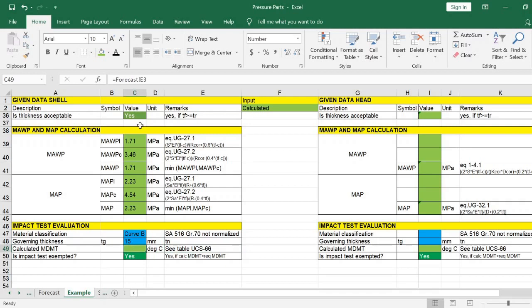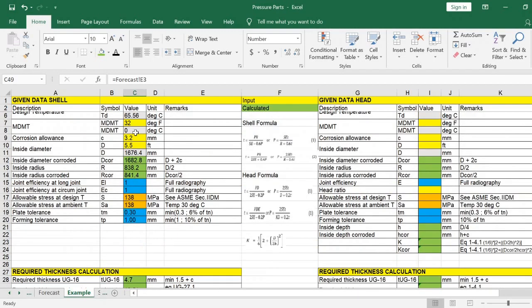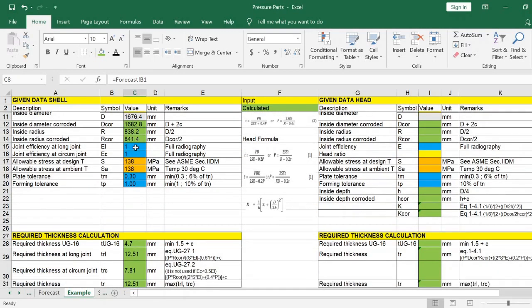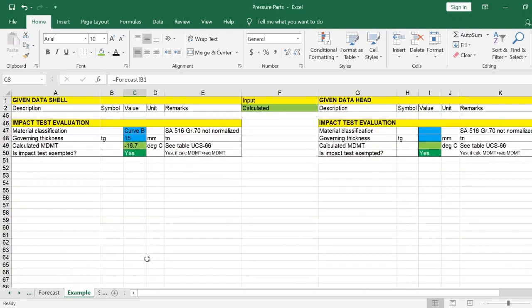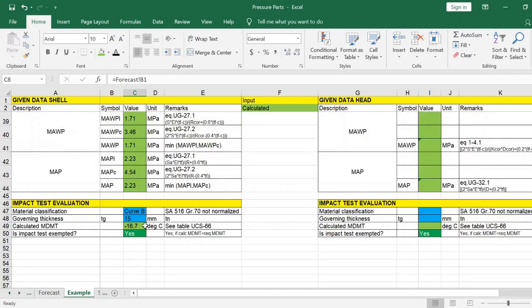So, we get minus 16.7 degrees Celsius. Lastly, we compare the required minimum design metal temperature of 0 degrees Celsius and the calculated minimum design metal temperature of minus 16.7 degrees Celsius. The calculated MDMT is colder than the required MDMT. So, the impact test is not required for the shell.